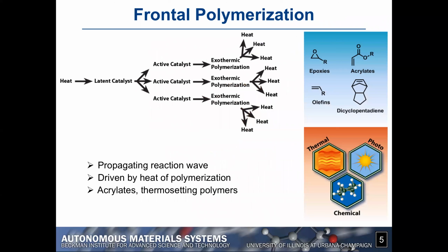So the idea is to introduce into the polymer a latent catalyst that is completely inactive until you introduce a small thermal trigger, typically in the form of a very small amount of heat. And that latent catalyst becomes active. And as it becomes active, it starts the polymerization, which is exothermic, and therefore creates its own heat, and therefore allows more of the monomer to be polymerized. Now, we did not invent frontal polymerization.